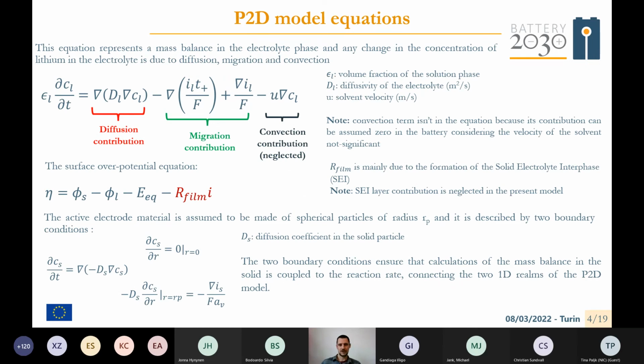I think we are near the end of this first part of the resume. So here I presented the equation that takes into account the mass balance in the electrolyte phase and the phenomena that influence this mass balance. As you can see, there are in the extended equation 3 terms: diffusion, migration, and convection. Take into account that the last term, that is convection, in our models and generally in models that are applied to lithium-ion batteries, is neglected because its contribution can be assumed to be 0, because the solvent velocity in this kind of batteries and system is not significant.